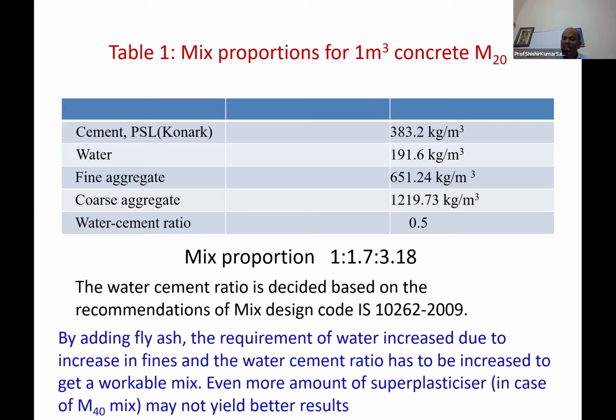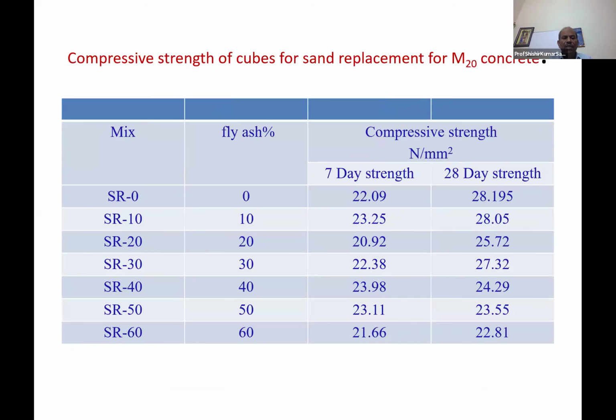So when you add fly ash, it becomes a harsh mix. So water is added extra to get a workable mix. Even more amount of superplasticizer has also been used in case of the M40 mix. Compressive strength of cubes for sand replacement.